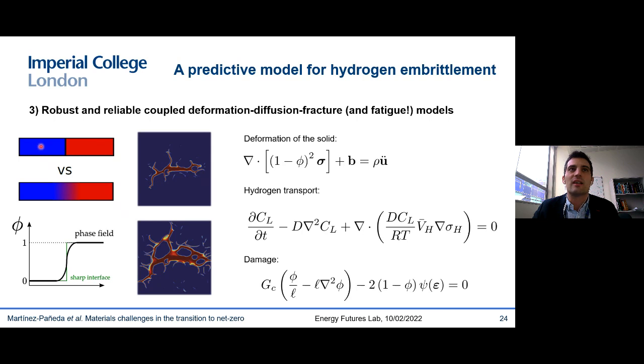But there's a very simple idea that we can exploit, this phase field paradigm that is quite convenient. So if you have two phases, let's say, for example, the crack is the red phase, and the non-damaged part of the material is the blue phase, you can think of them as having a sharp interface, or you could also smear the interface such that you can describe these two phases by means of a phase field variable. And this phase field variable will take, for example, the value of 0 in intact material and the value of 1 on cracks. And just by tracking how this variable evolves, we can capture all this complicated cracking phenomena.